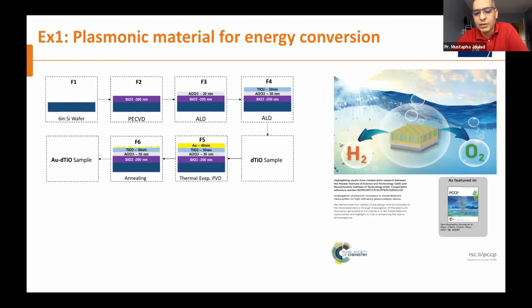So one of the examples, this is one of the works that was featured as a hot paper in PCCP. We implemented a composite material in order to produce clean energy as hydrogen by the water splitting technique. This water splitting technique is very well known. It's even a natural process, and it involves a semiconductor, basically titanium dioxide, which, when it is in contact with water, with impinging, for example, solar light, may decouple the atomic bonds in water, producing hydrogen in the conductive band and oxygen in the valence band.